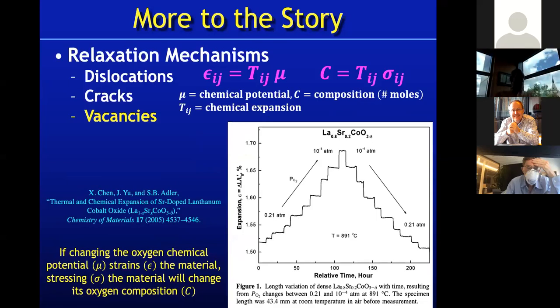I should point out that it's system dependent how large this coefficient, this second rank tensor T, is. In some systems, like the cobaltates, or systems where you're trying to stabilize some hard to stabilize oxidation state, the effective oxygen partial pressure can have a huge effect on the system. In other systems, lanthanum aluminate is a great example. Lanthanum is 3+, aluminum is 3+. Those are the only oxidation states that are known for those elements. So this tensor coefficient, although it is some finite value, is very, very small and can be neglected.